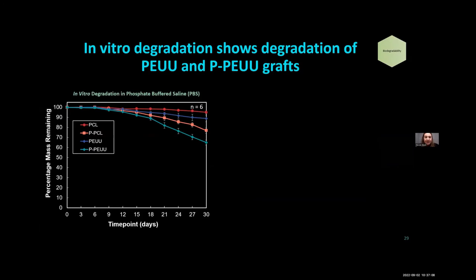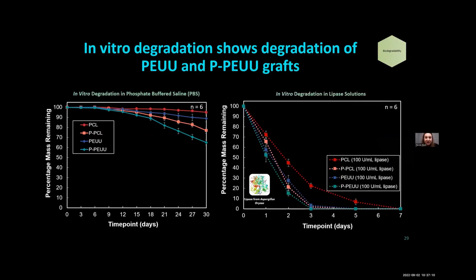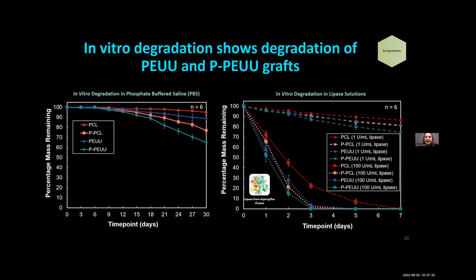Over time, as I mentioned, we're interested in developing something degradable. So really the benefit of this water-soluble component that we leached out was to increase the degradation rate of these materials. So you can see on the left in just a PBS solution, the PEUU materials in the front of them with that water-soluble component degrade at a faster rate than their counterparts without it. And this can be accelerated by, for example, testing grafts in a lipase solution to try to mimic the degradation that occurs in the body.